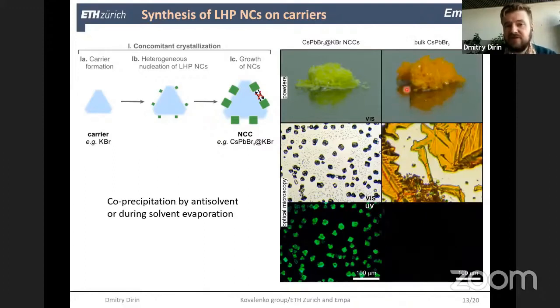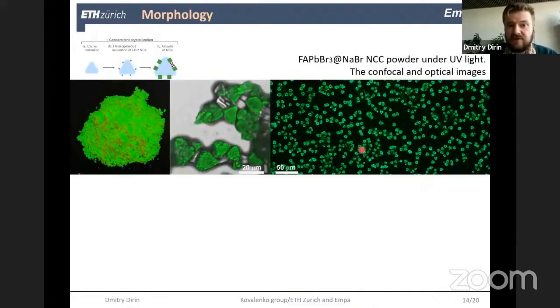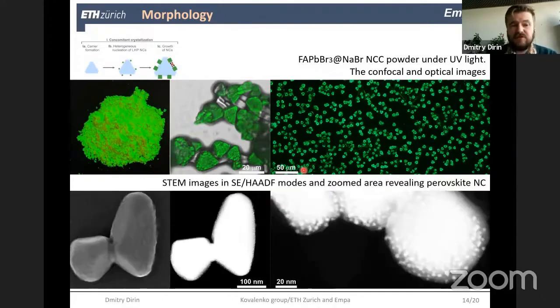For comparison, here I show you a photo of just bulk cesium lead bromide. No emission at all, as you can see here, and it's a different color. If we look in a confocal microscope, we can see microcrystals, nicely faceted, and the habit is typical for sodium bromide or KBr. If we look at electron microscopy images, we can see that we do have nanoparticles which are mainly localized on the surface of those carriers.